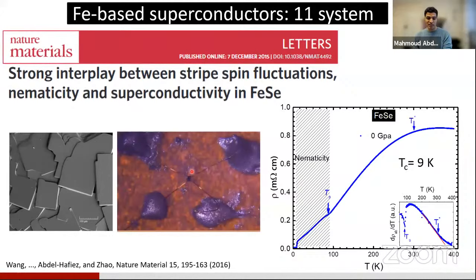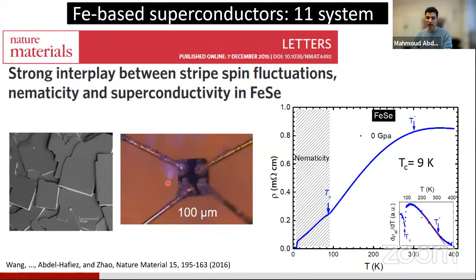So if you zoom out here, you will see the sample and also the connections here. The sample is 100 micron and this wire is a golden wire, it's 10 micron. We have to make these contacts, it's not a funny job, but it works very well. And once you make this, you can get a very nice transition from the temperature dependence of the resistivity. By doing X-ray here, we found that at this temperature, this anomaly, there is a structural transition. The system goes from tetragonal to orthorhombic. And as an indication of superconductivity, you see the zero resistance at 9 Kelvin. So that was very important.